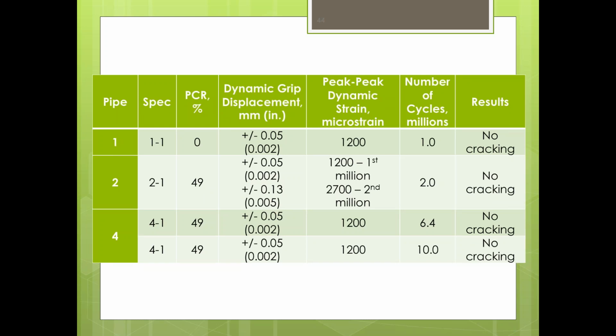So from a fatigue standpoint, you can see on the data here that the samples were tested up to 10 million cycles with no cracking observed, even when seeing a significant amount of post-consumer recycled resin in the pipe and in the samples themselves. The fact that there was no visible cracking and no recorded cracking even up to 10 million cycles yields to the fact that recycled plastics are really showing no difference from virgin in terms of their response to fatigue. They're excellent materials at handling repeated live loadings, and they're excellent materials at handling that dynamic strain that's placed on them and rebounding and staying in the position that they're supposed to be. So the net of his research was that fatigue is not a critical concern for recycled HDPE resins, any different than virgin resins themselves, which is a really great thing to see as well.